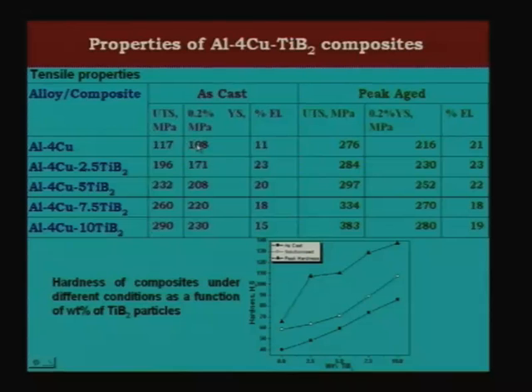And that is as far as hardness is concerned. Here we have the tensile properties. You can see aluminum copper as cast alloy has almost 117 UTS with about 11% elongation, and if you do peak aging, you get about 276 UTS with about 21% elongation. And then if you take about 10% of TiB2, with increasing percentage of TiB2, the strengthening increases. With 10% TiB2, you get about 290 even without aging itself.